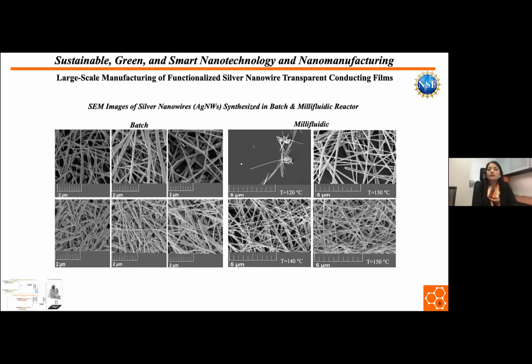However, if you take a look at the other 4 SEM images, which show silver nanowires produced in a millifluidic reactor, you can see that we got 100% silver nanowires without any other nanostructures as byproduct. We were also able to produce silver nanowires at a lower temperature compared to the batch reactor. For example, silver nanowires can be produced at 130 degrees C, which is not possible in a batch reactor, because for the batch reactor, the minimum temperature we need is 150 degrees C.